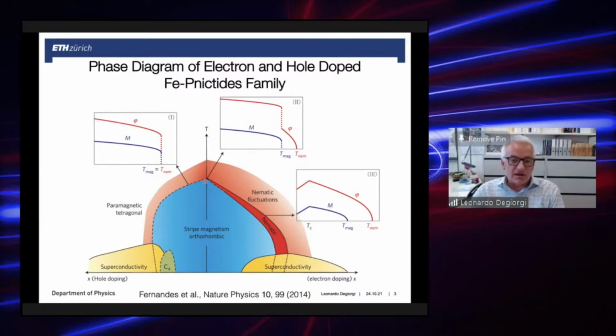Now, such a structural phase transition may coincide or eventually precede the phase transition into a magnetically ordered state, possibly due to some stripe magnetism. The point that I would like to make here, and which is going to be of relevance for my presentation, is that there are several experimental evidences pointing out that there is a rather broad temperature interval extending above the nominal temperature for the structural phase transition, which is characterized by nematic fluctuations, and this all the way up to the optimally doped regime.